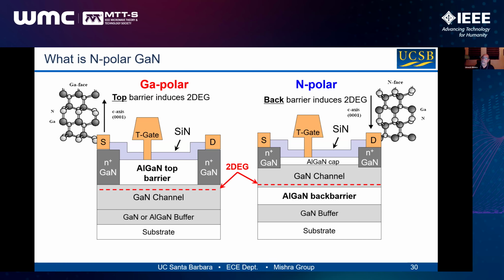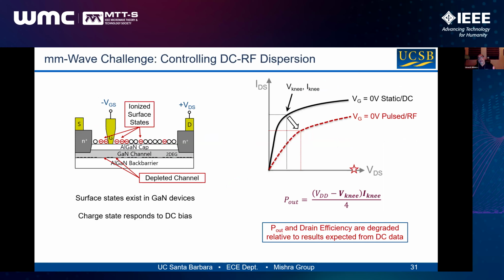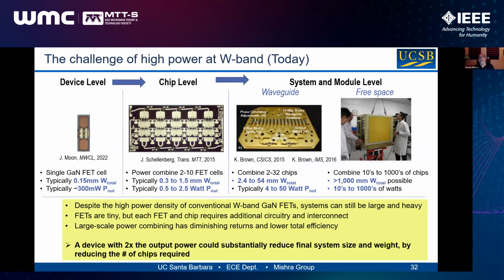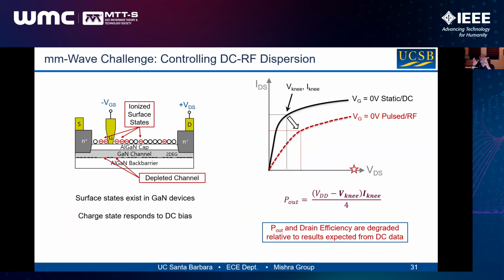And in my group, we decided to take this and basically develop a whole new class of device. And there was another thing. Remember, I talked about surfaces, and remember, I put silicon nitride on there to solve the problem. Well, with nitrogen polar GaN, you have a different way of solving the problem, and that is by a GaN cap. Okay, but we needed to do this nitrogen polar GaN. We had to have a target market. It's very important to know why you want to do it from a first insertion point.